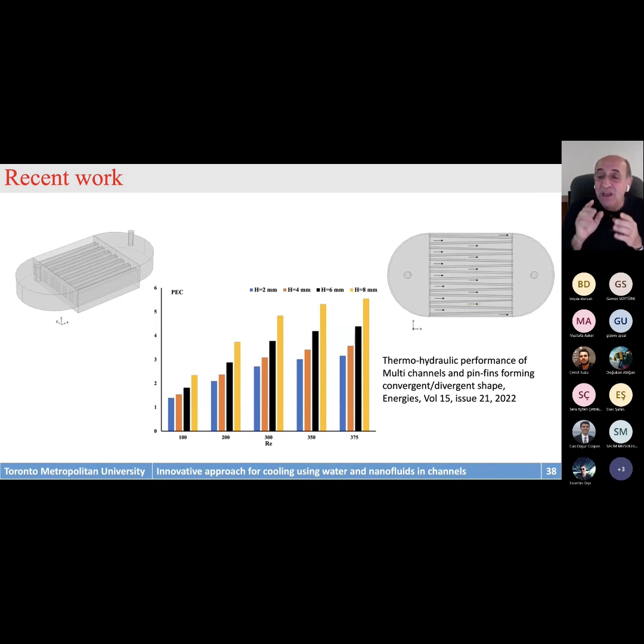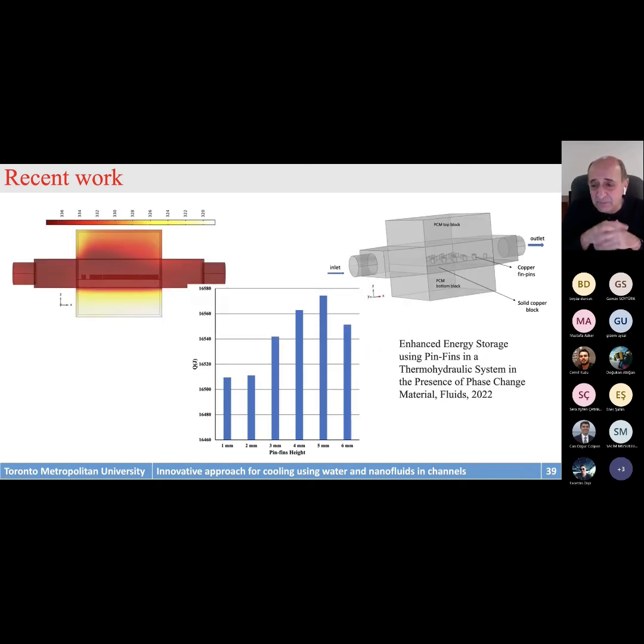Now, Professor Ho did some experimental work which we compared with, but in his experiment, he did not have a divergent channel. He had only a convergent channel. Here we allow both, but we noticed that the convergent is the most effective. And then we did it also for different heights, and we noticed that if we go to a height of 8 millimeter, it has the better performance evaluation criterion.